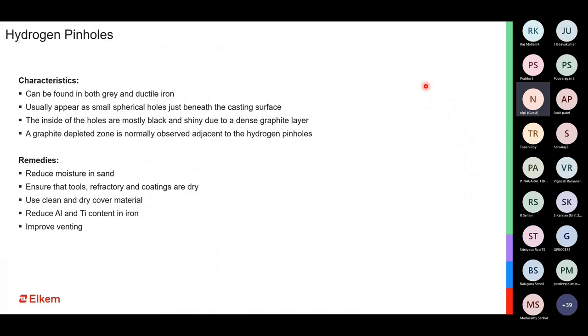How do you resolve it? But before resolution, we need to understand where it comes from. One of the main parameters which causes hydrogen pinhole is excess moisture in the sand or the sand system. Of course, not just the sand, also the presence of moisture in the coatings or the refractories, or any such part of the mold which is in direct contact with the iron or the casting. So we need to make sure that we do not have excess moisture in our sand, refractories, and coatings, and that they are sufficiently dried before we put them into use.